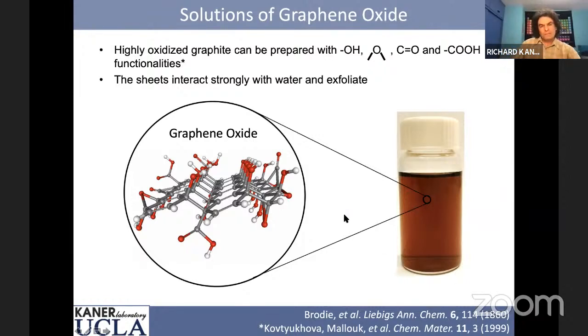And what's been known about graphene oxide is if you take graphite and you oxidize it, and something like nitric acid and potassium permanganate as an oxidizing agent is quite good, what you do is you put carboxylic acid groups and hydroxyl groups and epoxide groups, and then it disperses in water. And what we've learned in the past dozen years is it disperses in water as individual sheets. Now, of course, these are not conductive, they're insulating sheets, but if you could deoxygenate them, you can get back to graphene. And so this is a way to produce massive amounts of graphene.